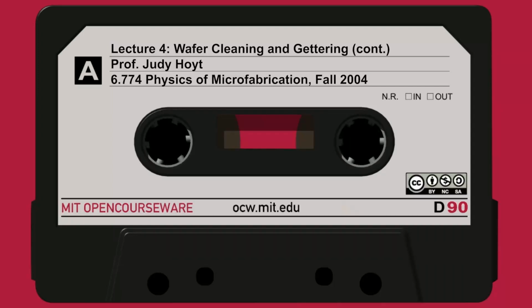That's bad because if you accidentally get copper on the back of the wafer, where you say, oh, it won't hurt anything, and you put it in the furnace, well, it sure will. It'll be in the front really quickly. It's good if you're trying to getter, because if the copper happens to be in your device region, you can try to get it to the back of the wafer, and the key is to hold it there. So it's both good and bad, but the fast metals are very fast diffusers. And copper's kind of an extreme example.